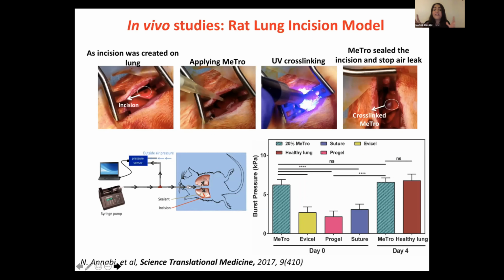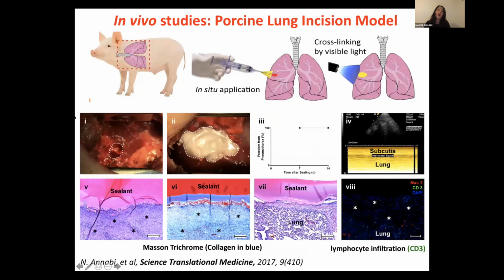So to further confirm this data, and to see if Metro can be used for clinical application, we moved on from a small animal to a large animal. And this time our model was pig. So we form a defect on the pig lung, and then we spray our hydrogel and photopolymerize it for a short period of time. And then here you see the defect on the lung, and this white part is a polymer that cross-linked on the surface of the tissue. Once we sealed the defect, we did ultrasound every other day to make sure that there was no leak from the lung. And also after 2-3 weeks, we did lots of studies to see how the tissue healed. And we also wanted to assess the inflammation as we apply this material on the lung.